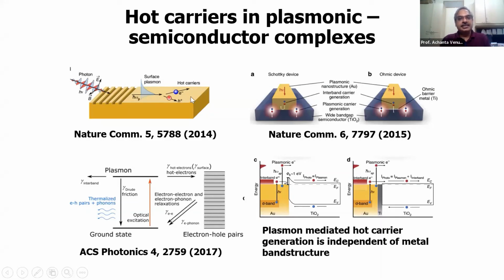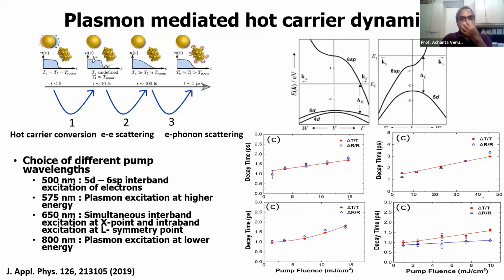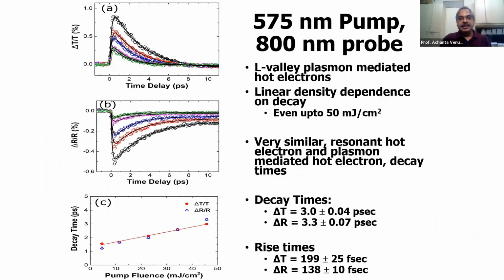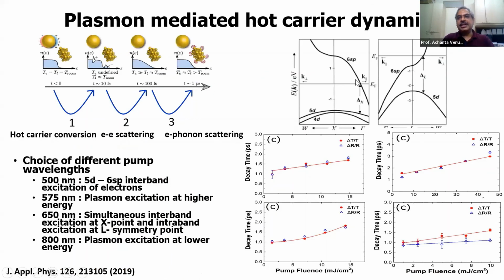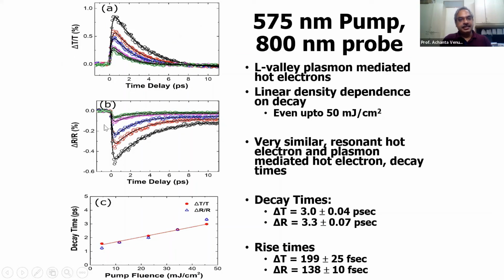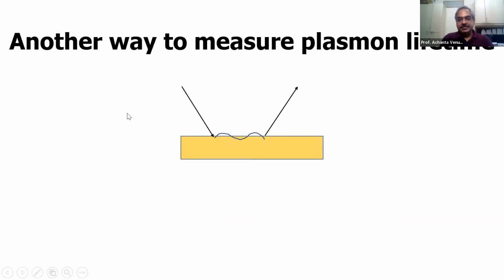People said that it has a large number of applications involving catalysis. You can have local doping and other things. So the basic question we can ask is how does this plasmon to hot carrier conversion take place? We studied this using pump probe techniques and showed that actually the bulk band structure of the gold matters. We did the pump probe measurements and showed that you can have scattering into different valleys, and interfering pathways will lead to different pump fluence dependencies in the decay times. We can also fit these temporal profiles to get all the time scales involved in each of the processes.